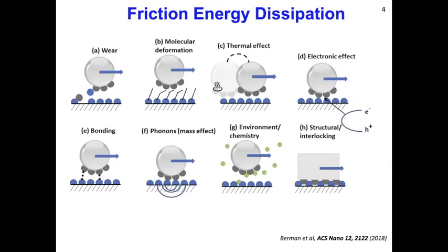What we know about friction energy dissipation, we try to highlight in these eight different mechanisms that are usually responsible for the losses we observe in mechanical systems in sliding conditions, generating more friction. First of all, wear: whenever we have a change on the surfaces, we need to supply the energy for this to occur, and this energy is lost as frictional energy. We could have some molecular deformation happening on the surfaces. Again, we need to supply more energy for this to happen, and this could be due to compression in the system, or elongation and stretching on the surfaces. So with this one, we are also losing energy.